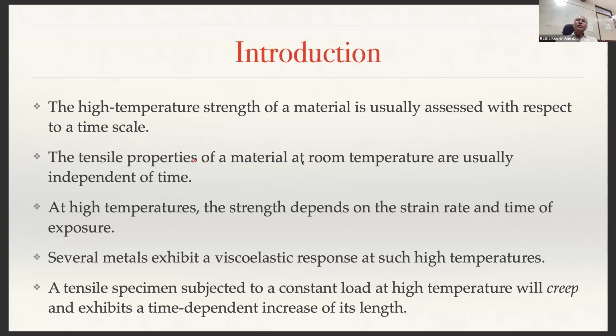And the tensile properties, if you measure at room temperature, are independent of time, but high temperature strength will be a function of time. That means at that particular strain, if you are operating for a sufficiently long time, the load the material can withstand at that strain will come down. So that is very important. That is what we call relaxation of the material. And again, at high temperatures, the strength of the material depends on the strain rate and time of exposure. The material strength depends more severely on the rate at which you are loading. And because we are dealing with metals, they normally exhibit elastic properties at room temperature, but at high temperatures, several metals exhibit viscoelastic response, very similar to polymers.